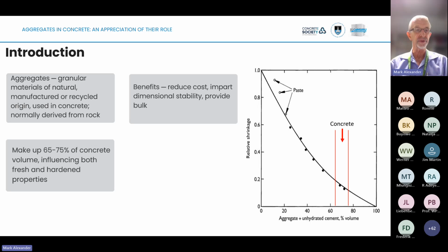And the important thing here is that they make up a large proportion of the volume and the mass of concrete, somewhere between 65 to 75%, sometimes a little bit more, sometimes a little bit less, but that's a general rule. And as you can see in the figure to the right, that's where the concrete fits in. And for example, an ordinary paste, pure cement paste, fits in right up at the top.